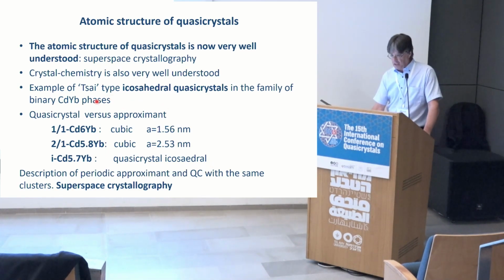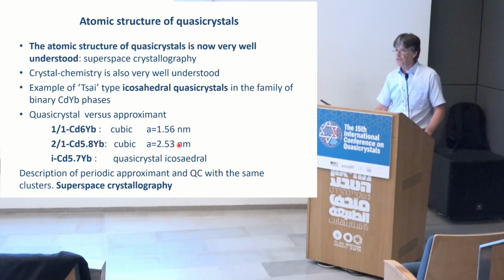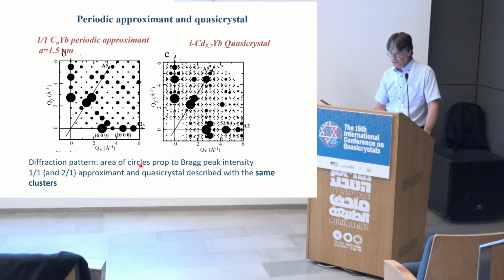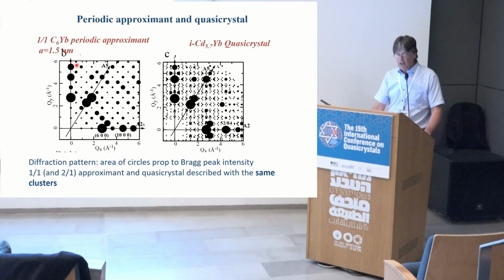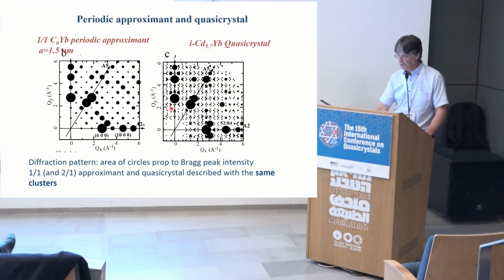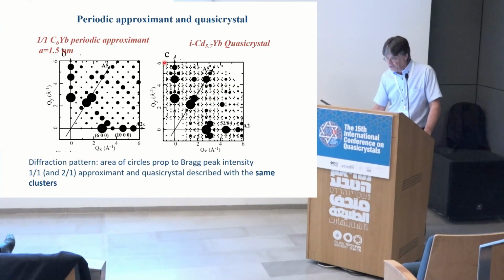the cadmium-ytterbium case, where we start from cadmium-6-ytterbium, it's periodic, 1.5 nanometer, 5.8 cadmium-ytterbium, it's still periodic, 2.53, and if we change slightly, 5.7, all of a sudden it becomes icosahedral, non-periodic, but yet well-ordered. And this is shown here. So this is a two-dimensional section of the reciprocal space. This is the periodic one. You clearly see the periodicity, 1-1 approximant. And this is the quasicrystal, no periodicity.